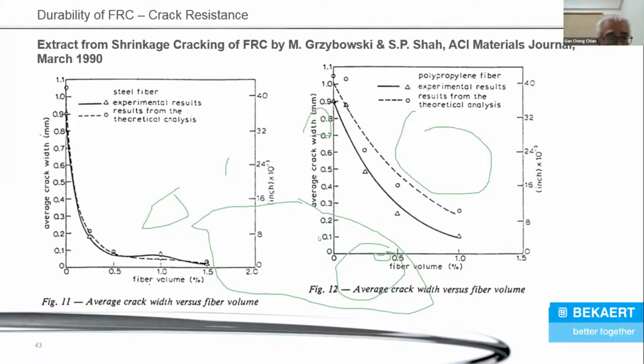It's so long ago. Okay, look at figure 11. Let's say you are using 0.5% of fiber. 0.5% of fiber is 40 kilograms of steel fiber. So if you bring this line up to this curve, you will find that the average crack width is 0.1 millimeter. So when you use 0.5% of fiber by volume, which is 40 kilograms per cubic meter of concrete, you can already achieve 0.1 millimeter crack width. This was confirmed in March 1990, not now. And then this curve, figure 12, this is for polymer fibers.